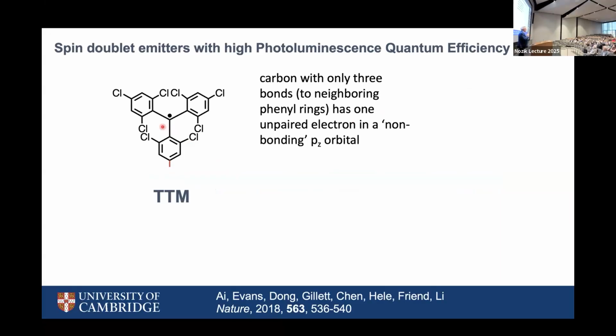But there are perfectly stable structures where we have only one electron in what ought to be a doubly occupied or unoccupied orbital, where the redox potentials are in a perfectly sensible zone, the same sort of range that we use in standard organic semiconductor electronics. And a motif that has proved pretty useful is this one here. The acronym I'm going to use is TTM. We have 3 benzene rings, they have chlorines on, which are linked onto a single carbon.